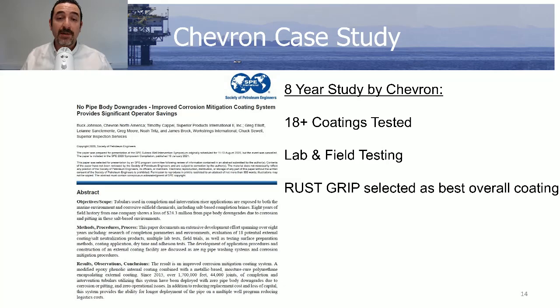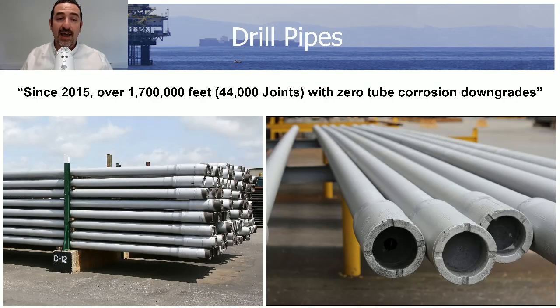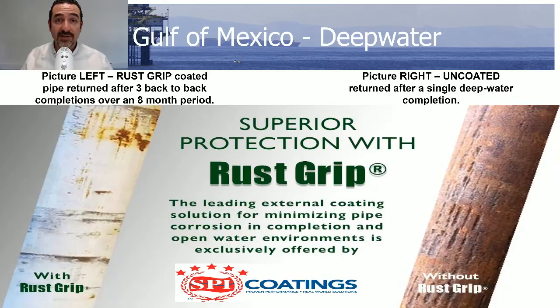So really, here's what that looks like. And since 2015, we have 1,700,000 linear feet with 0 tube corrosion downgrades. Picture on the left, pipe returned after 3 back-to-back completions. The picture on the right, after a single completion, and you can see the amount of corrosion.